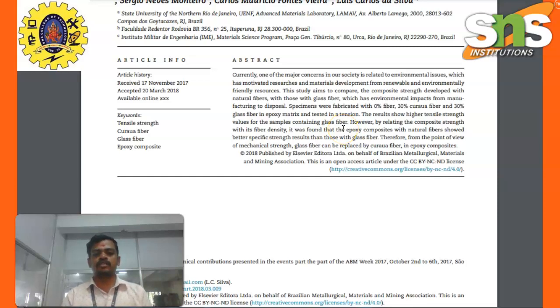Today, the case study. One of the major concerns in our society is related to environmental issues, which has motivated research, materials, and development from renewable and environmentally friendly resources. This study aims to compare the composite strength developed with natural fibers and polymer fibers, the glass fibers, which have environmental impact from manufacturing and disposal. Specimens were fabricated with 0% fiber, 30% curaua fibers, and 30% glass fiber in epoxy matrix and tested